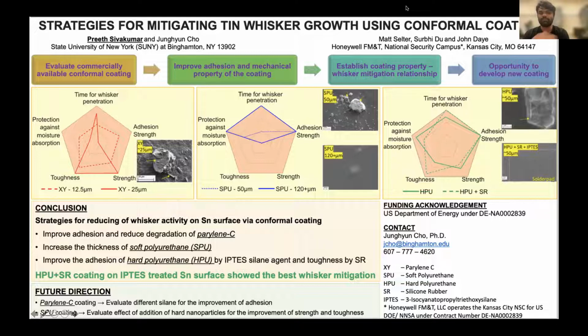So the future direction of this work is parylene coating. Because of the adhesion strength, the whisker mitigation is not that good. So we are going to try different silane agents in order to improve the adhesion strength of parylene C coating. And also the thickness of soft polyurethane is way too high, above 120 microns. So we are trying to add some hard filler materials to increase the strength and toughness of the coating, so that even with a thinner soft polyurethane coating, we can get better whisker mitigation behavior.